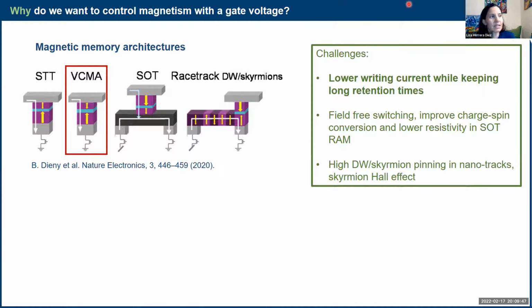And then there are other things that are more particular to each type of design. For example, the spin orbit torque type of memories, where we need to have field-free switching, improve the charge spin conversion, and lower resistivity. Or in racetracks, where we have domain walls or skyrmions, we need to really control the pinning, and for example, the skyrmion Hall effect as well, that needs to be controlled in order to use skyrmions on a track for information storage.